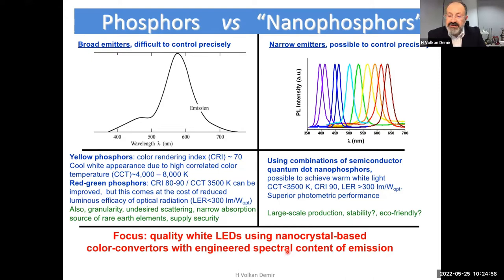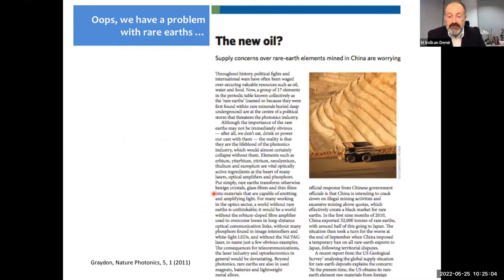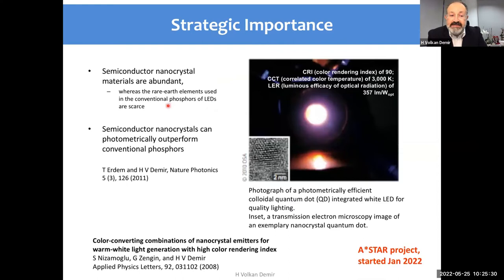And this was indeed a debate that came out in the photonics community about 10 years ago, showing that this type of conventional color converters known as phosphors, including rare earth elements, is an issue because this is available in only certain countries and used as an international negotiation chip because you can't find it all around. On the other hand, semiconductor and nanocrystal materials are abundant. And we were asked to contribute to this discussion in the community, pointing out that semiconductor nanocrystals can also photometrically outperform conventional phosphors. And today, this is among the best performance achieved in terms of color metrics, again, obtained using nanocrystals, in this case, colloidal quantum dots.